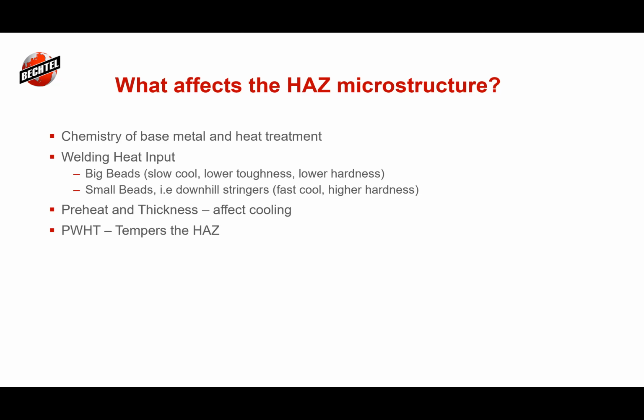If you have a really thick piece, then you're going to be pulling the heat out really fast from where you're welding, and it can have the effect of quenching that weld metal. The thickness can actually act as a quench on that weld metal. So it's always important to think through what your cooling rates are, and maybe even use some thermocouples, or at least some temp sticks, if nothing else.